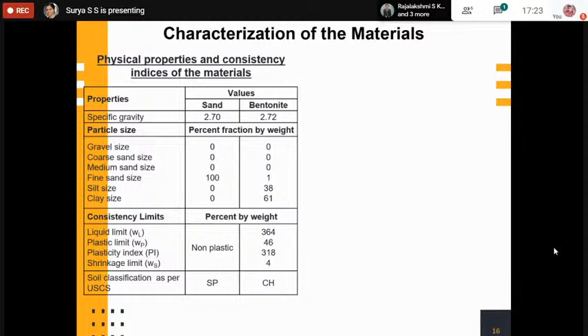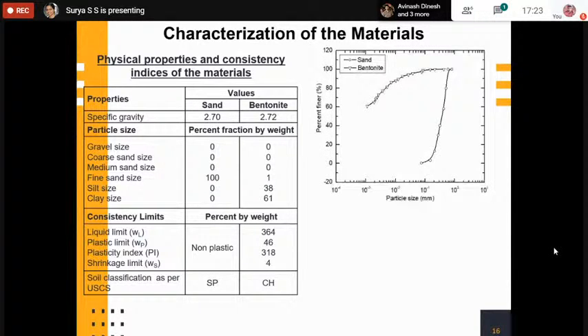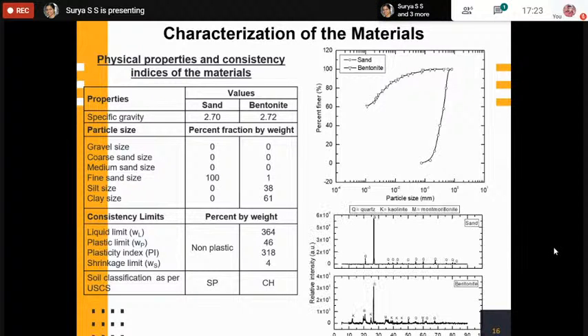So I could find that my clay is highly compressible clay with a high liquid limit of 364, which tells me that it is a highly reactive bentonite. And this figure shows the grain size distribution curve. Since I have used fine grain sand, only one range of sand particles I have selected. So you can see that this kind of curve you are getting. And this is the X-ray diffraction pattern, which I have already shown before.